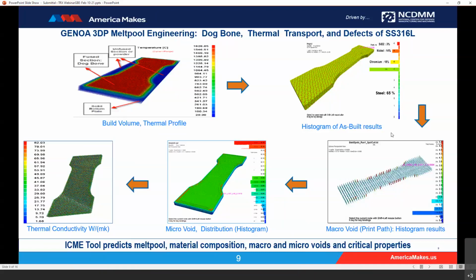The bottom right and the bottom middle show the macro and micro void content of the virtual dog bone specimen as built. Finally, the image on the bottom left provides a prediction of thermal conductivity of the dog bone at the end of the printing process. The significance is that ICME tools predict melt pool, material composition, macro and micro voids, and other critical properties such as thermal conductivity.